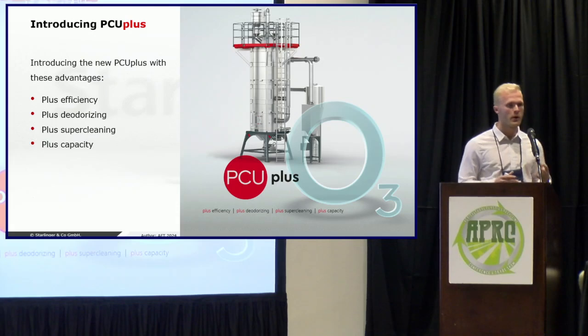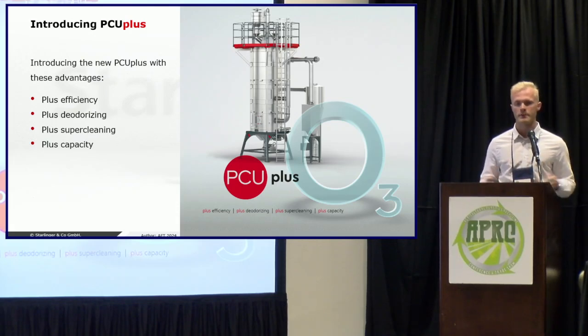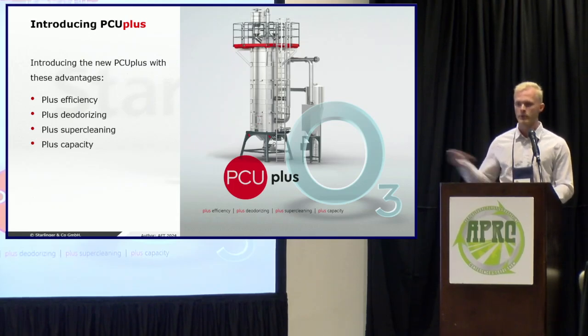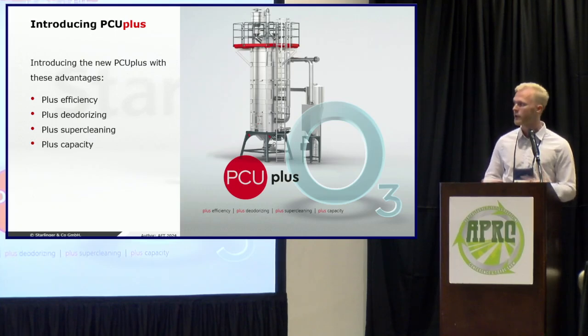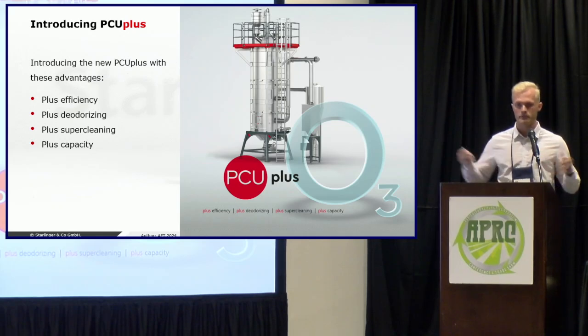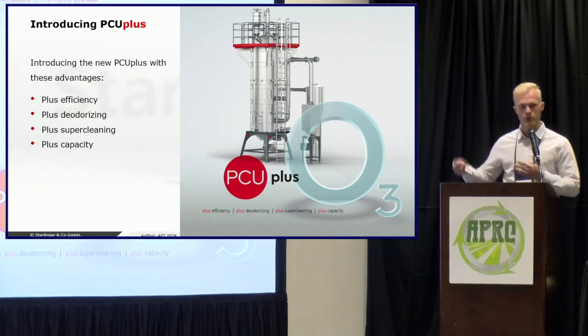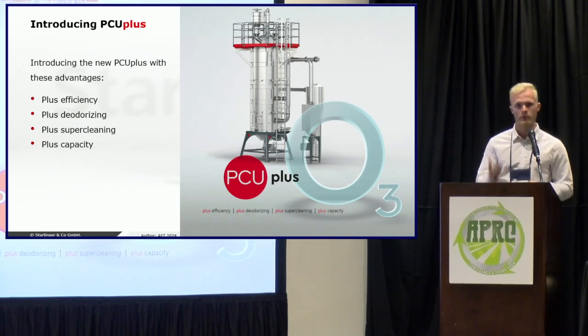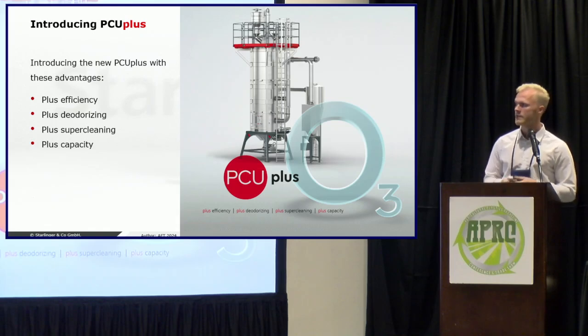And this is a learning that we've applied from our knowledge in the PET bottle-to-bottle space. So we do a similar process with our SSP units under vacuum and with nitrogen. But of course, here we're using overpressure and temperature and with ozone. So when those contaminants migrate to the outside of the pellet, there's a hot air flush with the addition of the ozone gas that will then come through the bottom of the unit and actually shift the pellets around, therefore latching onto the contaminant and removing it from the system. So with the PCU Plus, we've added efficiency with temperature control. We've added extra deodorization and super cleaning capacity, and we've added an additional larger sized unit.